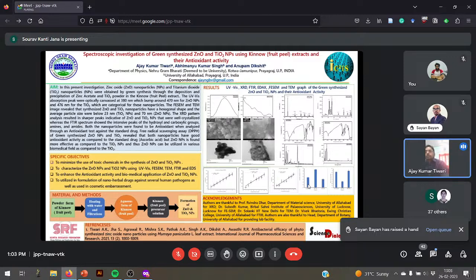Material and method: we have used powder form of the Kinnow fruit peel, heating this powder with water, and fabricated it to get the aqueous form of the Kinnow fruit peel. Then we get the Kinnow fruit peel precursor solution, and then the formation of zinc oxide nanoparticle and titanium dioxide nanoparticle. Here, as the end result, various spectroscopic techniques we have used to characterize these two nanoparticles. We have found their UV-vis, which we discussed earlier. Now, antioxidant activity, I'm going to explain about this one.